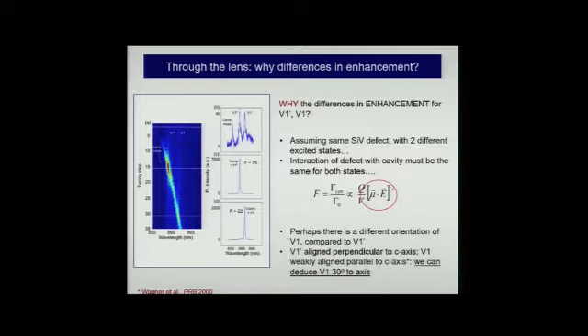So V1 prime gives us the higher enhancement. V1 is excitation to an excited state that's lower in energy. Why is the enhancement so different? This is what the cavity should do to it. Maybe this factor is different. And maybe the orientation of that excited state, whatever the wave function looks like, may be slightly different. If we do a very simple-minded calculation, which may not be warranted, that suggests that maybe V1 prime is aligned along the C-axis. Maybe V1 is slightly off-axis. Now, this is a supposition, and there's lots more work that needs to be done. But the important thing is, imagine understanding what the spatial distribution of an excited state wave function looks like by looking through this lens.